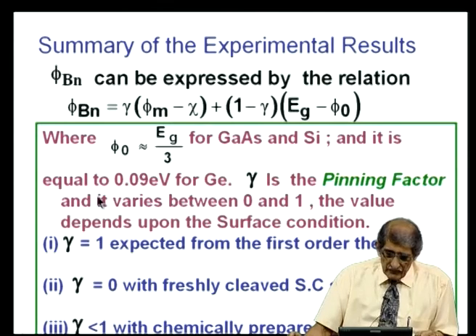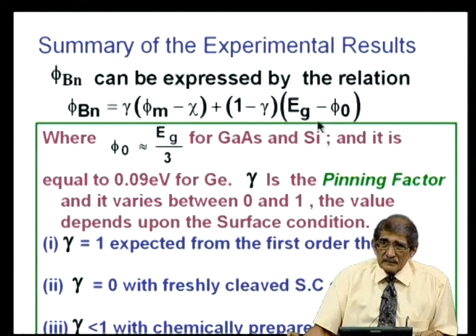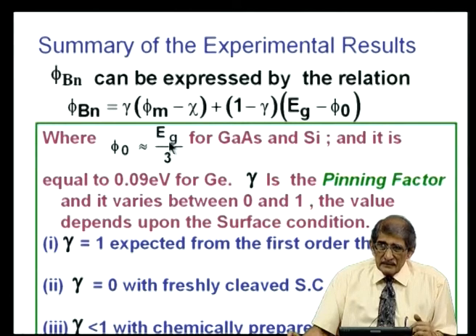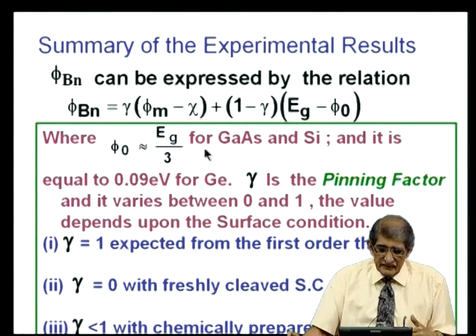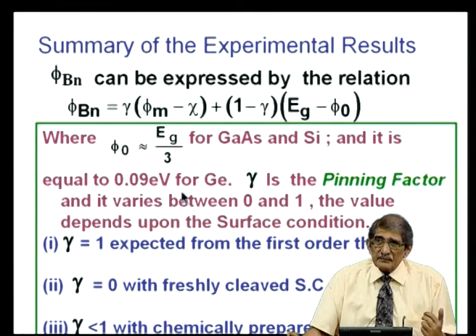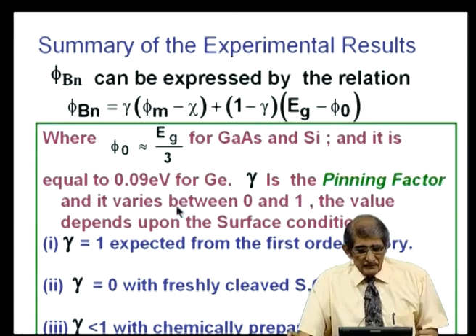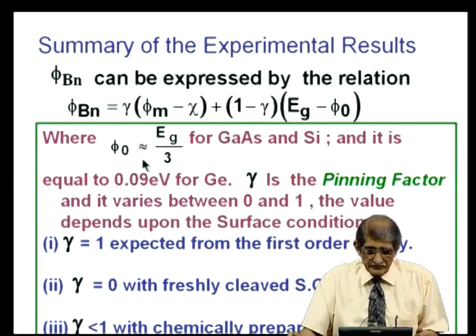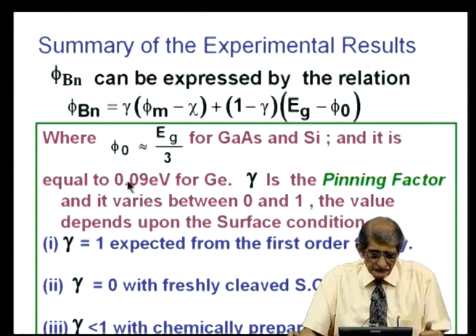This phi naught is actually, as we discussed earlier, the neutral level. It is the energy difference between the neutral level and the valence band. For silicon and gallium arsenide, that is E g by 3. And in germanium, it is equal to 0.09 electron volts, where the band gap is 0.66 electron volts. This phi naught is very close to the valence band. We will see more about that now.